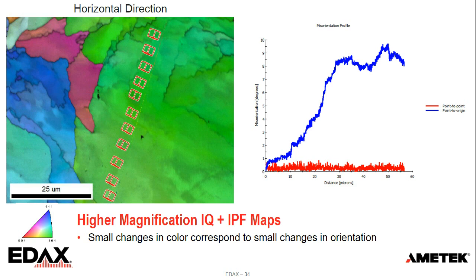And we can see that on the profile on the right, the misorientation profile. The red line shows the point-to-point misorientation. So from point to point, the misorientation is not changing a lot. But if we look from the bottom to the top, there's a cumulative effect of how that misorientation has developed throughout that grain. There's some structure to that misorientation.